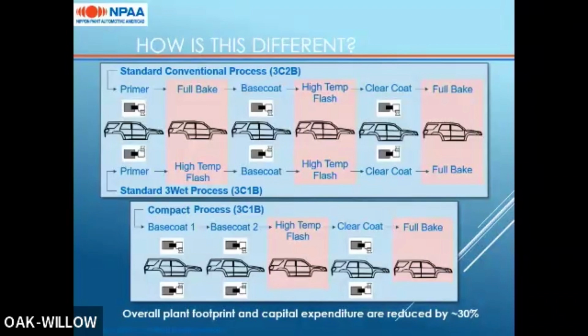Okay, and the very last question from the app. Your target film build of 6 to 8 microns for base coat layers is on the order of thickness variation we would like to see over a vehicle surface. How do you manage film build and color uniformity? We work with the customers or OEMs to ensure that they have application settings that can be met. So adjusting the bell speeds, flow rates, shaping air, anything along those lines.